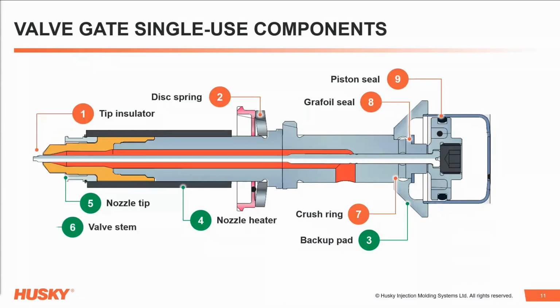Finally, the valve stem controls the gate itself. This is a continuous use part, and it can be used so long as it's not damaged. Stem positions should be checked to ensure that they close all the way, but the condition of the stem should also be checked because worn stems can lose their shutoff and gate quality can suffer, which is often a critical part feature.